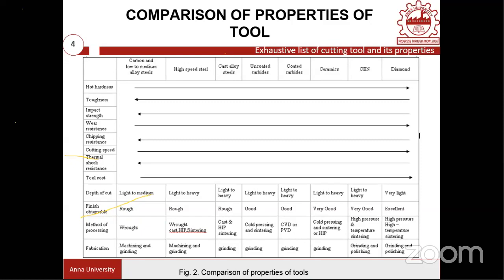If you look at the chart, light to heavy cuts are possible with ceramics, cemented carbides, CBN and diamond. The finish obtainable is very good for most of the ceramics, and for diamond it is excellent. As for the method of processing, cemented carbides depend on hot isostatic pressing, or consolidation followed by sintering, whereas all the other advanced tool materials, for example CERMETS, cubic boron nitride and diamond, are manufactured by other methods.